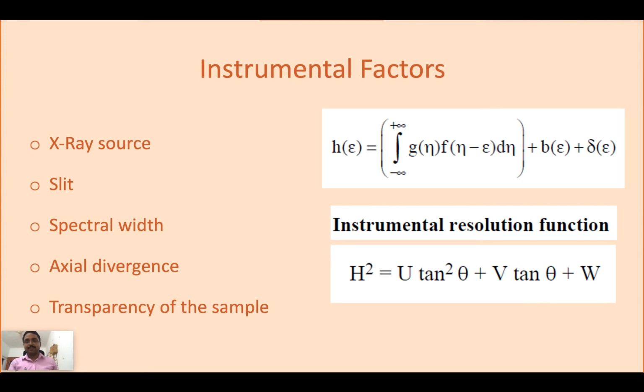So instrumental factors, now I told you, not only the sample but also the instrument contributes. For example, X-ray source, slit, spectral width, axial divergence, transparency of the sample, all these are very important terms. I am not going to explain these things. I gave you the book, you can refer there, but my point is these things will contribute. That is what we define as the instrumental resolution function. So what the instrument operators will do is they will run a standard sample, for example copper, aluminum oxide or some similar standard samples. If they are running these standard samples, you will get a standard peak width, that is your full width half maximum. If any change is happening to that, the instrument will be adjusted for your standard sample.